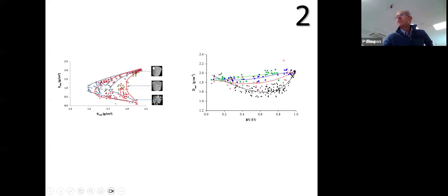Here we have very solid or cortical bone. If you look in this spectrum, you can see that the material density of bone changes with the apparent density. It's not all the same. And it changes by quite a lot, actually, 1.5 to 1.9 grams per cubic centimeter. So basically, what this tells us is that when bone remodels, it doesn't remodel at the same rate everywhere.